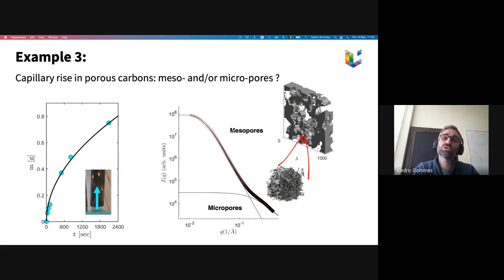So really, you have these two families of pores, mesopores and micropores. And when you do capillary rise experiments, so you dip this particular porous material in water and measure the weight, you see water gets in, but it's mostly the large pores that contribute to the weight. And so the question is, where does the water go? Does the water enter the micropores at all? And for many applications, this is central because most of the surface area is in the micropores.